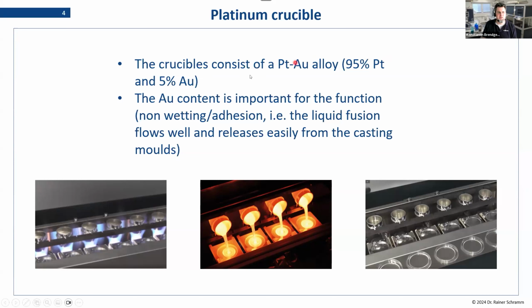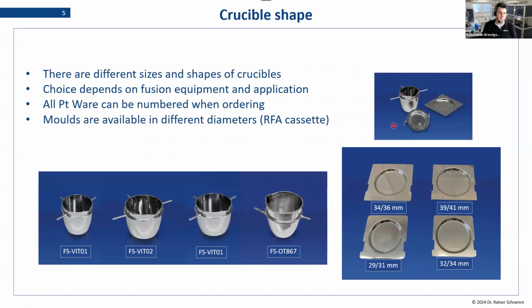So coming back to our specific alloy, the gold content in these crucibles and molds is extremely important. The gold prevents our liquid fusion from sticking with the platinum. This is especially important in the casting molds. The gold prevents the fusion from sticking to the surfaces of the dishes when it is cooling down and solidifying. So you want those 5%, and over time, we'll come to that a bit later, this changes, and then at some point you have to be doing a recycling cycle for this. So one thing to keep in mind, the gold is critical here because it directly affects the function of our platinum ware when it comes to the fusion and the fusion machines.